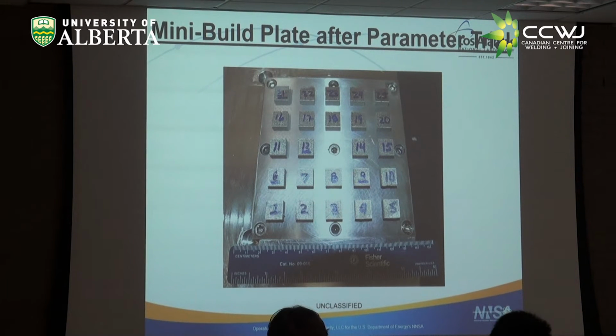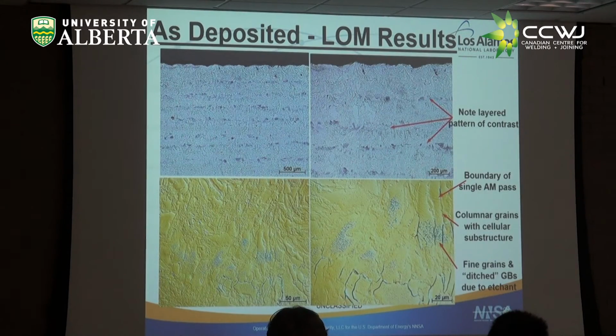So we had this 5x5 sort of matrix and then began to look at the effect of the parameters on what we're looking for, which is full density first of all, and then our properties later. We looked at the phase diagram a minute ago, and I made a point to remember the continuous cooling transformation diagram because that was important. After processing and coming back to room temperature, we would expect all this martensite, which we would then go back and temper. Well, big surprise, we have none of that pretty much. So I'll show you the as deposited material.